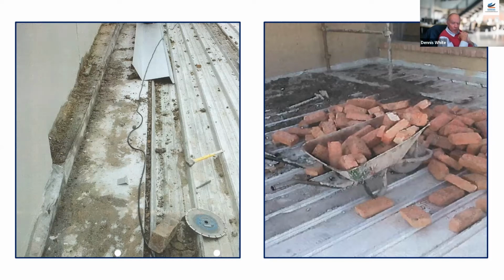That happened on the surface of a roof after it was installed, but a similar scenario can happen if you're adjacent to building works with a bundle of cladding that's being stored. So those surfaces are a problem from the mechanical point of view, particularly if you get wet mortar on a metallic surface, because there's a chemical reaction between the wet mortar and the surface of the cladding, which can lead to premature corrosion.